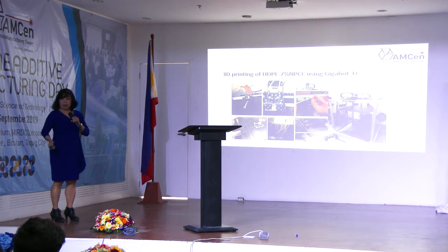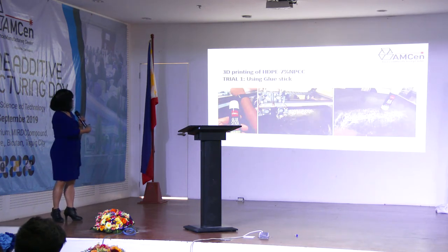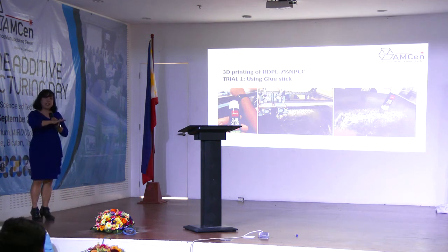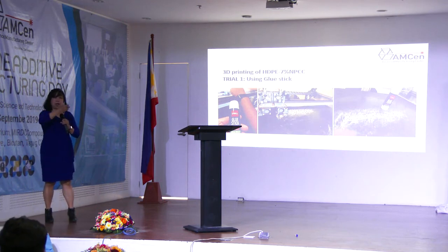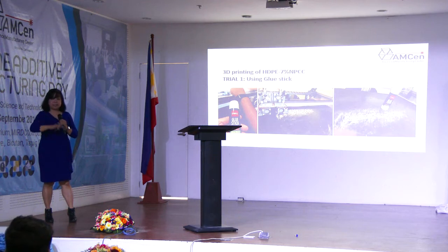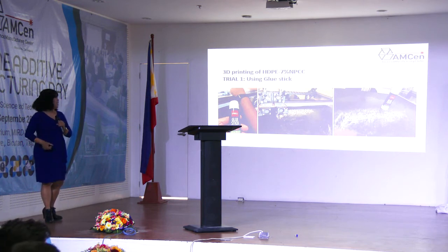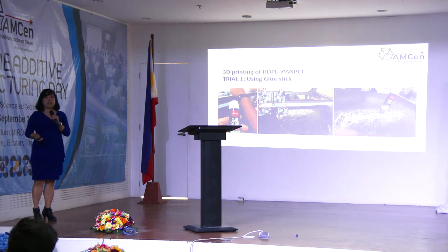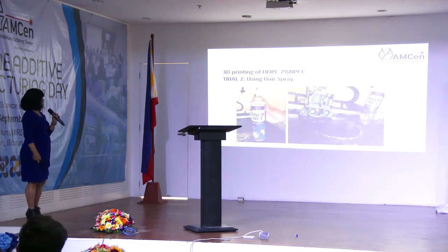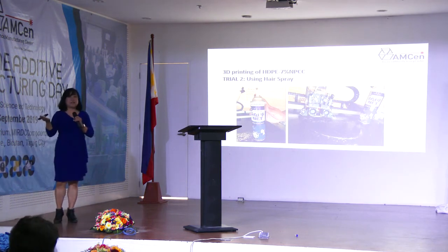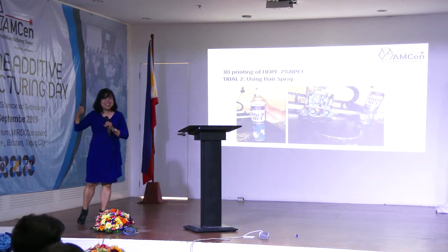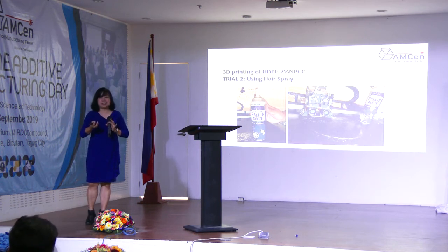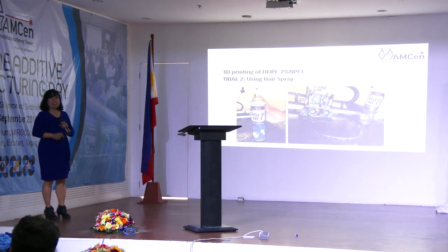Okay, so since it did not stick on the build plate, we tried to use glue. There were studies that you need a coating on the build plate for you to be able to print and have your object stick on the build plate. So we use a common glue stick. But just the same, there was no print on the build plate. That was the first trial. Then we used the hairspray because we learned that spraying a spray net on the build plate will help hold the sample. This is the strongest hairspray that we bought commercially, but still, initially it stuck on the plate, but when the spray dries, it detached from the build plate.